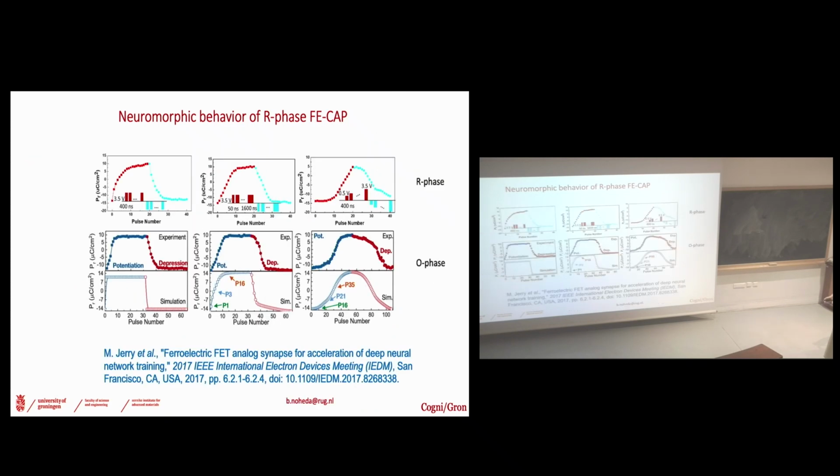What we find very interesting about this is that if you compare what we got with our rhombohedral epitaxial fully oriented hafnia, and you compare it with what people have got on polycrystalline orthorhombic ALD grown non-oriented hafnia, it is very similar. So in ferroelectrics you don't expect this. The symmetry of the material is everything. If you change the symmetry, the polarization changes completely. You don't expect to have anything similar. What happens in hafnia? Why do we see different symmetries and the properties are so similar? It's actually another big question we have.